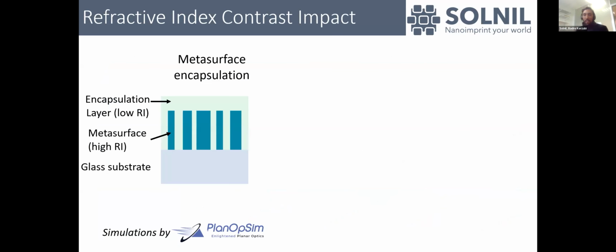So now if we come back to the refractive index range that we can cover, why is it important to have such a refractive index contrast? Usually when you work on a metasurface, the base building component is what we call a meta-atom. So you have these pillars, usually of high refractive index materials, and you play on the dimension to have a full coverage of the phase, to develop your metasurface. And usually for integration into a product, you need some kind of encapsulation layer to protect this metasurface from mechanical damages and to have better integration into your product. And what is important there is the refractive index contrast of this encapsulation layer with the metasurface.